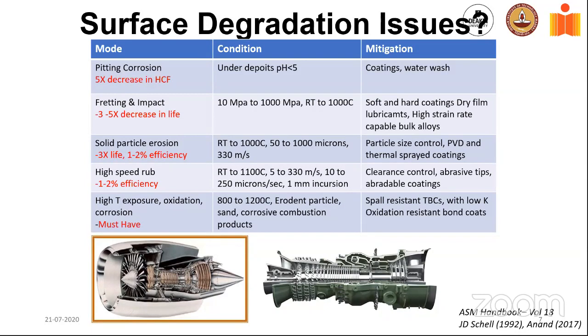But what happens is that you have a wide range of operating conditions, as the table shows, all the way from 10 MPa stress to 1000 MPa stress, room temperature to 1000 degrees Celsius for fretting and impact. What would be the solution for fretting and impact? We have a complete suite of coatings, and I would really recommend that you look at ASM Handbook Volume 18, 1992, and also ASM Handbook Volume 18, 2017. I was asked to write a review article for wear and erosion issues on gas and steam turbines. And so between aviation and gas and steam turbines, the entire aspect of tribology essentially gets discussed in these chapters.